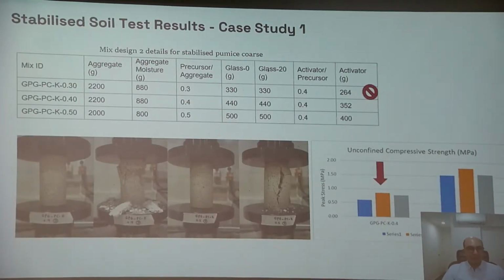This optimized mortar then was used with the problematic soil pumice for the stabilization process, and the results have been achieved by the UCS tests. Different percentages of the precursor versus aggregate, or the binder versus aggregate, were used. The one that uses 30% of precursor versus the aggregate or the pumice was not successful because it was too dry. But the 0.4 and 0.5 achieved good results. As you see here, the 0.4 of precursor to aggregate achieved more than 500 kilopascal, and the one that had 0.5 of precursor versus aggregate achieved around 1.5 megapascal of strength.